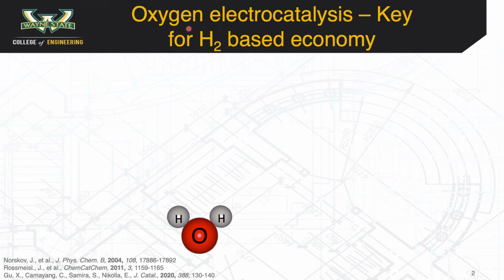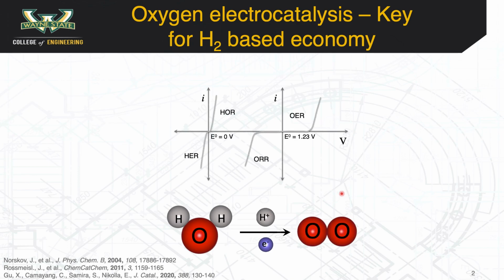Let me start off by discussing oxygen electrocatalysis and why it remains key for a hydrogen-based economy. The hydrogen-based economy primarily revolves around a carbon-neutral way of producing hydrogen and then consuming this hydrogen as the fuel. One of the cleanest and sustainable ways of producing hydrogen is via electrochemical splitting of water that results in oxygen as a byproduct. Shown here is a typical current potential curve associated with water splitting. It is observed that the deviation from the theoretical potential for oxygen evolution reaction is significantly larger than that of hydrogen evolution reaction, thus making OER the overall efficiency determining step in a water electrolyzer.